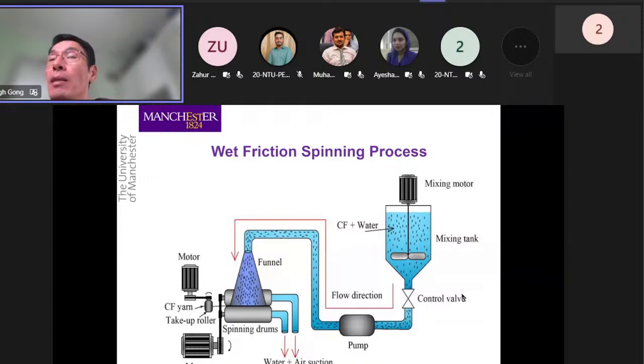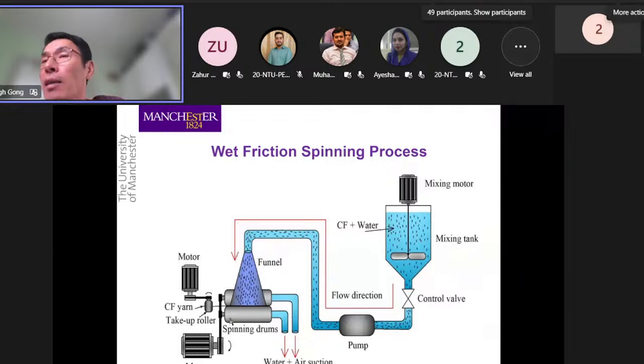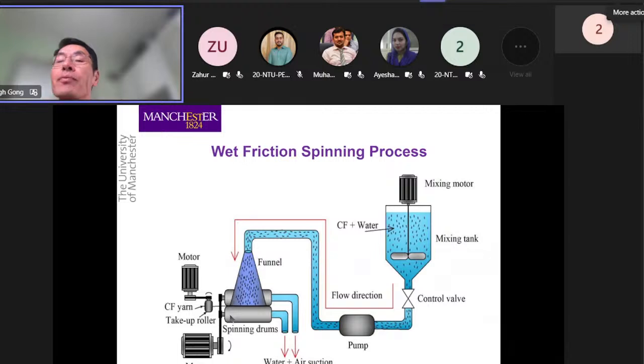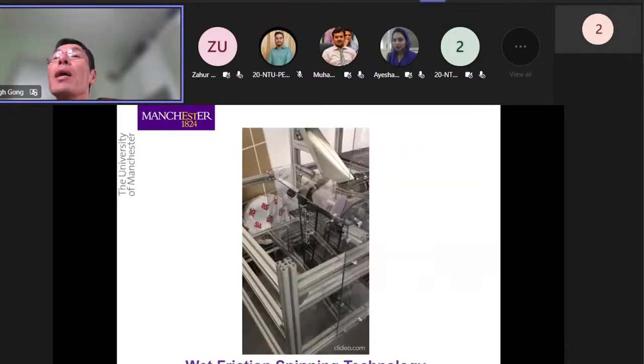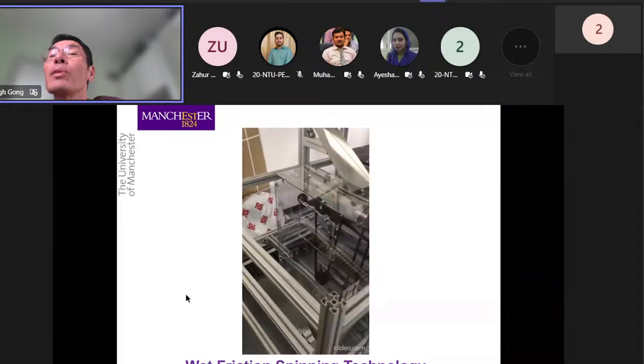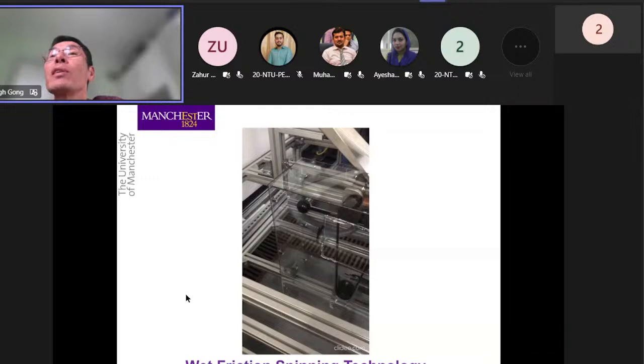So by dispersing the carbon fibers in a liquid, and then we transfer the liquid. Instead of using air, we use liquid. Transfer that to the friction drums. This way, we can contain the carbon dust, so there won't be any dust generation throughout the whole process. And that's the video of what we built, just to show you the machine we have built for this.